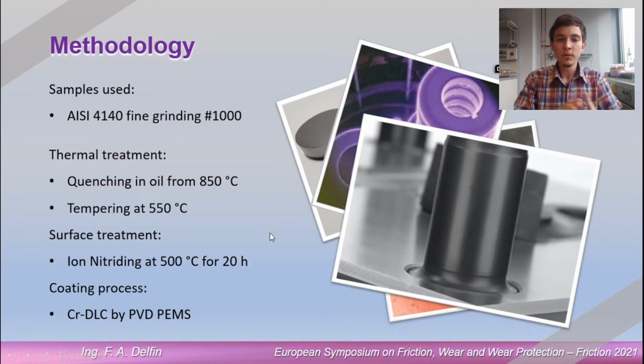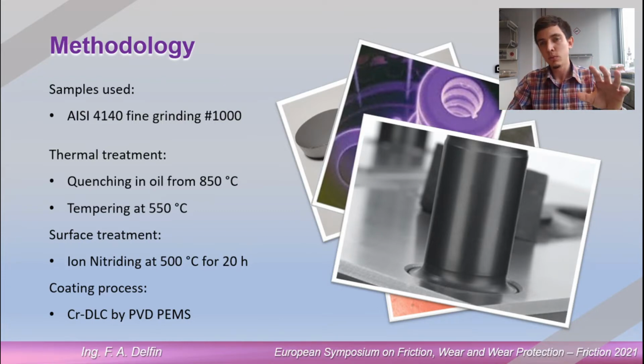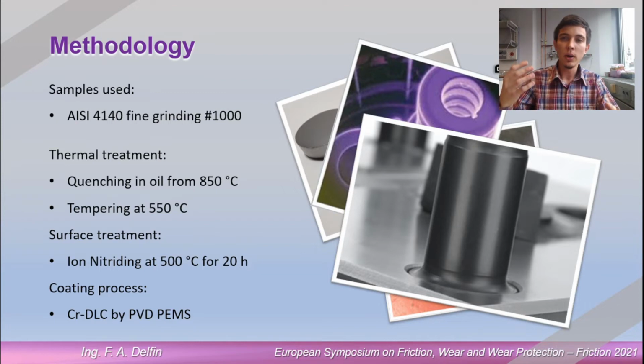Then we took a group of these samples and ground everything to 1000 grit, so it's not a polished substrate. We took a group of them and nitrided them at 500 degrees for 20 hours, and then we coated all the samples with this chromium DLC made by PVD plasma magnetron sputtering. So we have two sets of samples. One set is with the nitriding before, and the other one is without nitriding. The ones nitrided and coated we call duplex, and the other ones are only coated.